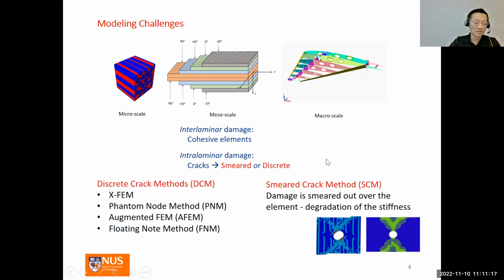Most high-fidelity modeling of progressive damage is conducted at a meso or ply level scale, in the picture shown in the middle here. Of course, you have the larger scales, the component and structural scale, the macroscale. And these models are usually modeled using shell or plate elements. At the microscale, you can explicitly model the fibers and the matrix material. However, these are usually of the order of micrometers. We can resort at the mesoscale to either discrete or smeared crack methods.